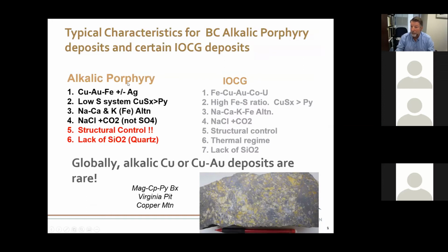And the real features of these deposits is essentially that they're copper-gold, high iron systems, plus or minus silver. We don't see cobalt and uranium like you do in some of the other deposits over here. They're generally low sulfur systems, so your copper sulfides are generally much greater than pyrite. You get sodium, calcic, and potassium alteration, but you see very little in the way of phyllic or argillic alteration. And this alteration is not zoned in a concentric zonation like it is in the calc-alkaline deposits, as we shall see.